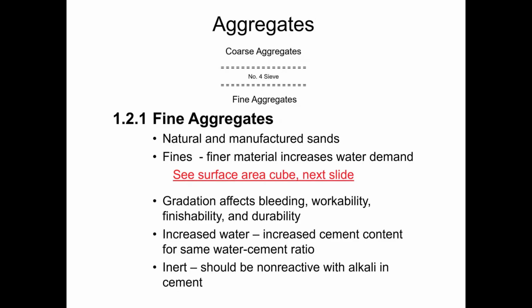All right, so the gradation of our fine aggregate is very important to us because a big part of that gradation is the surface area, and that dictates how much water and cement slurry we need to coat the aggregate particles. So if there's variation in the gradation of our fine aggregate, that can cause problems. If the gradation becomes coarser, then we may have excess water in our mix, which can lead to bleeding. The formation of water on the surface of the concrete, the placed concrete. If the gradation of our fine aggregate gets finer, then that can lead to a tightening up of our mix, a loss of workability, a loss of slump, because now we have more surface area that has to be coated by our cement and water slurry.